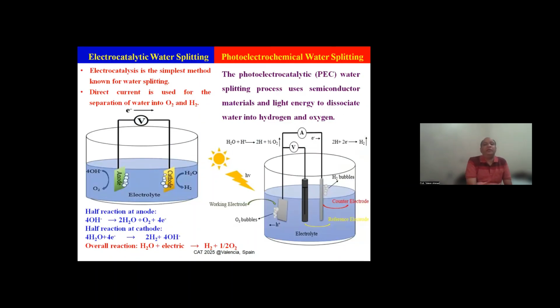oxygen. So another methodology that we use for water splitting is electrochemical water splitting. Electrocatalysis is the simplest method, which has been known for water splitting for a long time, where it involves a three electrode reaction where you can use direct current to separate hydrogen and oxygen. Generally, the hydrogen evolution reaction, HER, occurs at the cathode, whereas the oxygen evolution reaction, OER, occurs at the anode.